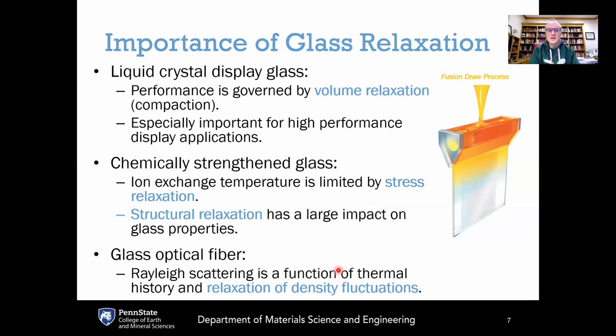All of this information is being sent at the speed of light through very thin strands of glass known as optical fiber. And the ability of these glass fibers to transmit this information is really governed by the Rayleigh scattering. And that is a function of how much the density is fluctuating within the glass, and that is controlled by the relaxation behavior of the glass too.